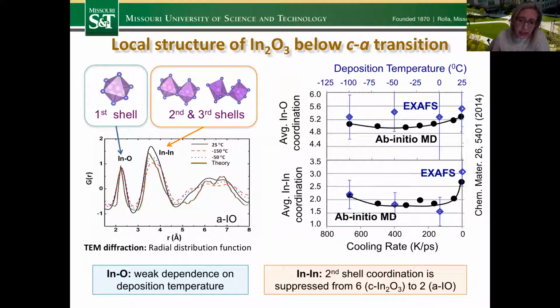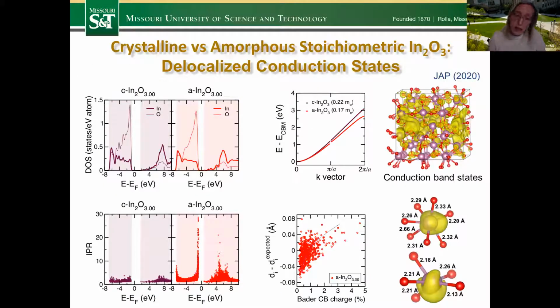What's fascinating here is that the second shell coordination is suppressed from nearly 6 to 2 in indium oxide, and indeed the edge sharing is broken. So from 50% edge shared, 50% corner shared, when we go to the amorphous phase, we switch to almost 70% corner shared and 30% edge shared pairs. Well, the first peak is not changing. So the indium-oxygen distances are similar, at least on average.